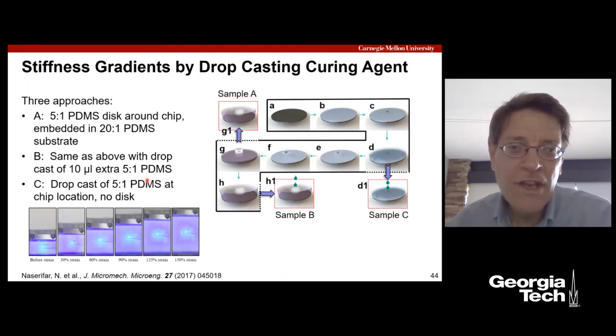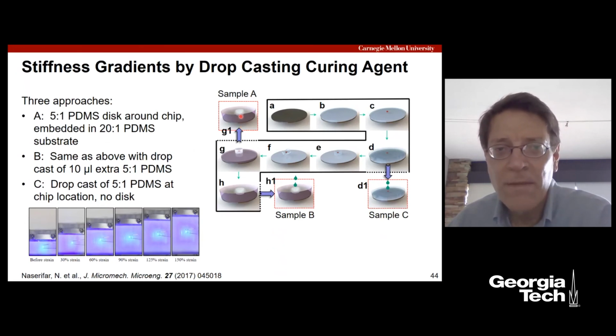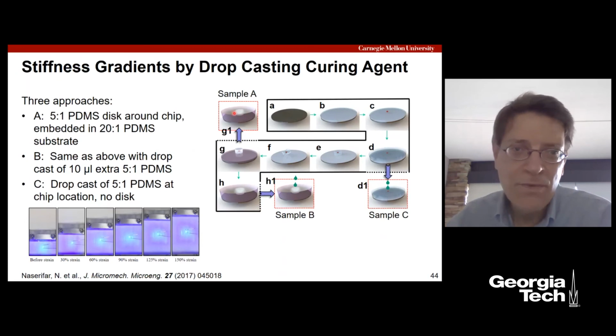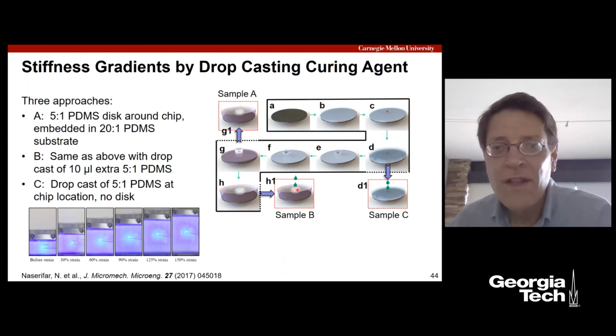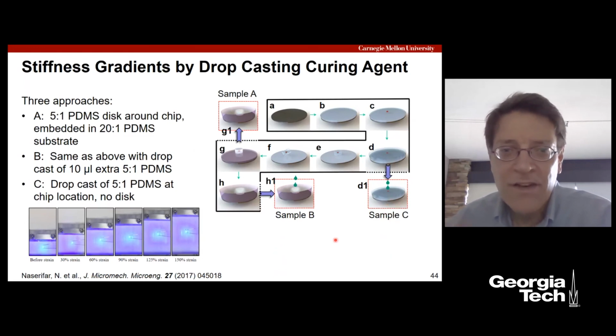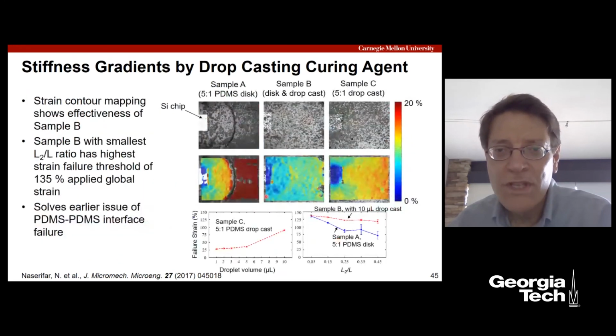Then we did another study where we took that a step further and said, well, can we drop cast, and what's the effect of drop casting PDMS as opposed to just creating solid chunks and embedding them inside? So we did a hybrid, where we had solid chunks of 5-to-1 PDMS, which is what we did previously, and that's a control. And then we drop cast 5-to-1 PDMS in addition, to make a diffusion region around that. And then we just tried 5-to-1 PDMS drop cast without any solid chunk in the middle, to see how that protects the chip.